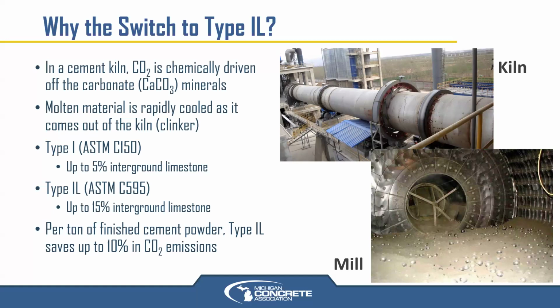But the majority of what goes into a cement kiln as raw material is a carbonate material. Calcium carbonate is fairly plentiful throughout North America. So the primary ingredient is limestone, which is typically the mineral we have readily available that has the calcium carbonate we need. That is kind of the workhorse. The main part of cement, as far as its constituents, comes from a limestone product that goes into the kiln and changes chemically through that very high temperature process.